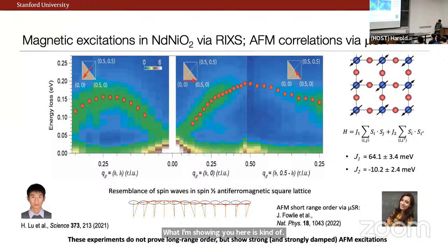What I'm showing you here is basic data along high symmetry directions of magnetic excitations in the system. So the first statement I would make is if you look at these red peak position data points, it looks quite exactly like you would expect if you had spin wave excitations in an antiferromagnetic square lattice. So just in cartoon form, imagine that this was my ground state. Thinking about it just like in the phonon problem, excitations of that spin lattice, this is the kind of thing you would see. And in fact, you could map this very much into a simple magnon type of problem with near neighbor and next nearest neighbor interactions.